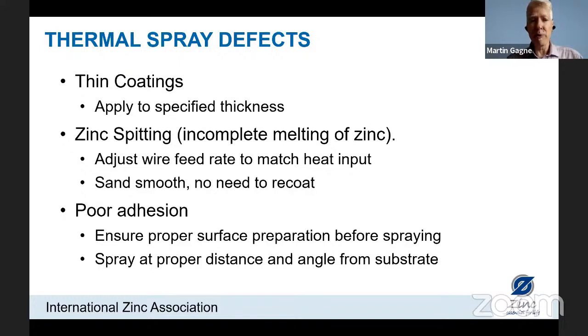The remedy is very simple. We just sand the coating. It removes those lumps of zinc. There's no need to recoat, or they can be left there if the surface quality is not an issue. If this is the interior beam on the bottom of a bridge, you just have more zinc available to help with corrosion protection. But if it's an exposed beam and we want to have a smooth surface, we can just sand those defects and they will disappear.